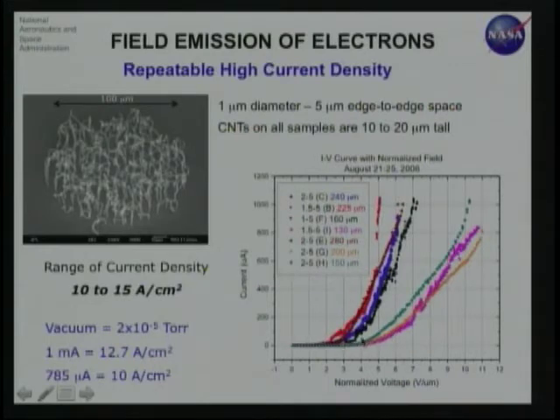And look at the sharpness of the knee of this curve itself. This is the normalized voltage, so they're all in the 2 to 6 or 2 to 8 volts per micron range. The reason for two of these groupings here is these samples contained very high gammas, tubes with very high gamma, more than 7,000. On this side are the ones which had an amplification factor of about 4,000. So they clearly distinguish to tell you how important having a very high field enhancement factor is.